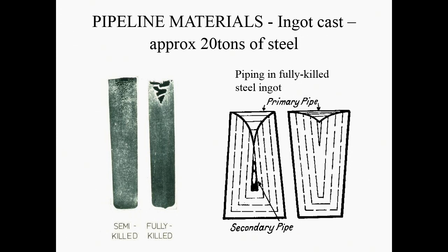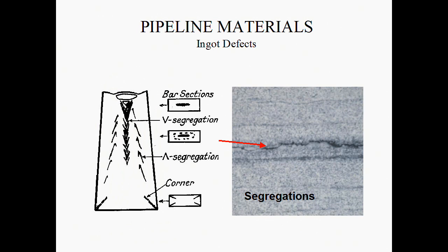You'll sometimes find laminations, little lack of fusion defects right down the middle of the pipe. And it often comes from this primary steel making process and the fact that the homogenisation process hasn't taken place and there's still a layer of impurities in the system. And we'll talk a bit about laminations later on. Actually, they don't have a big effect on pipes, so we tend to ignore them unless they're sufficiently large. But they are primarily a function of the steel making process. You can actually look at these defects,